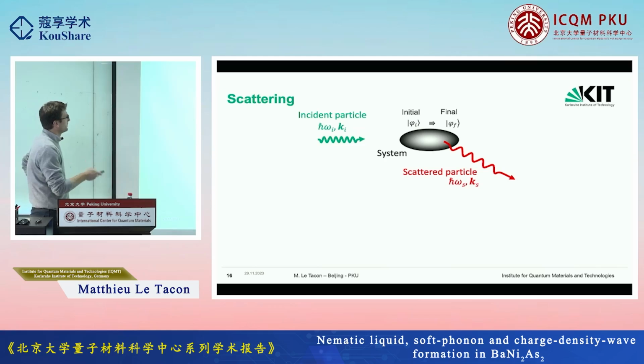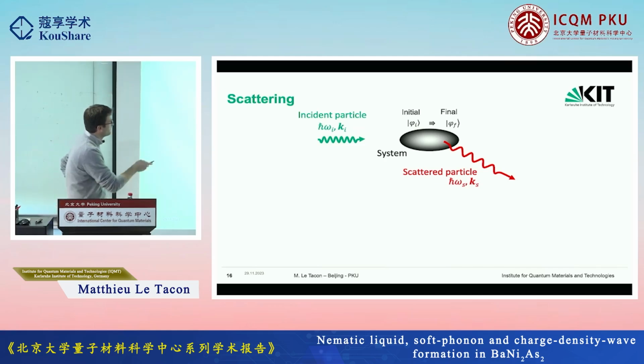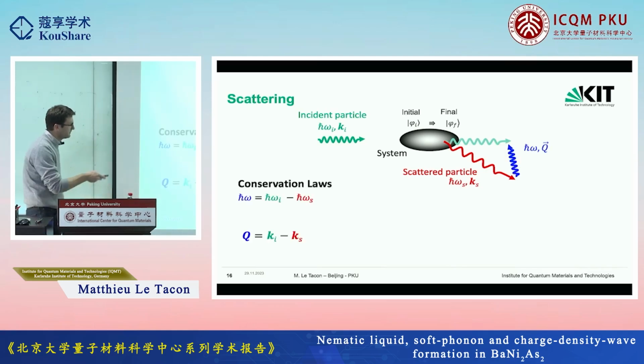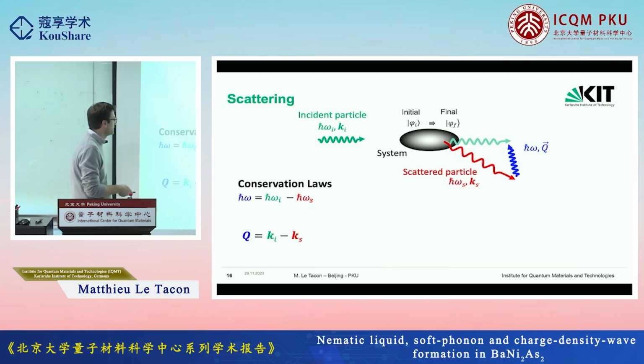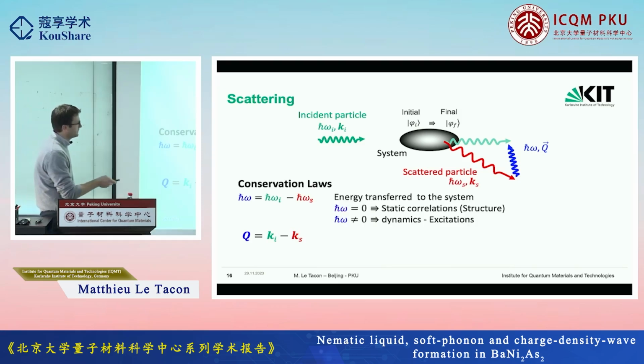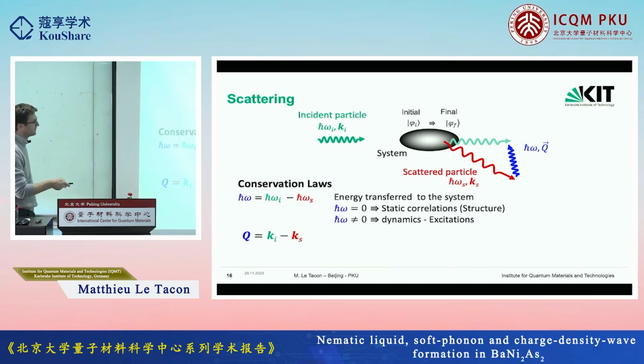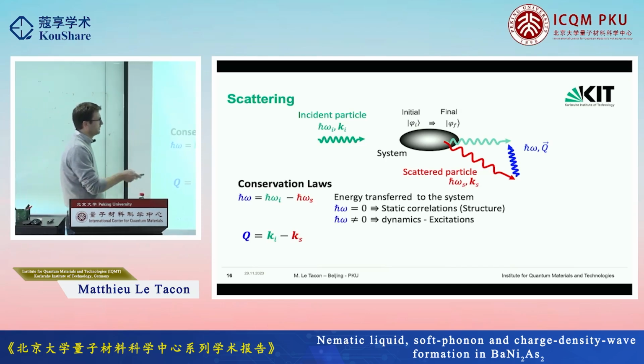The idea is to start with an incident particle and have this particle scattered by the system. During the scattering process, the system is brought from an initial to a final state. There is eventually an energy and a momentum transfer, and we have to satisfy the conservation laws. The energy has to be conserved, so you can create some excitation in case you have an energy transfer, and you look at the dynamics of the system. But you can also look at static correlations, or the structure, if you look in the elastic channel.